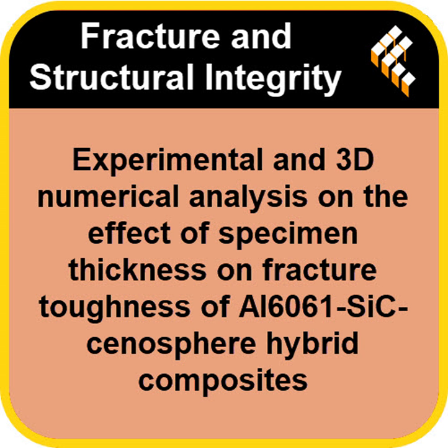Absolutely. Good practice. The researchers performed 3D finite element analysis, FEA, using ANSYS software. They used it to simulate the stress intensity factor, the SIF, at the crack tip. And the results from the simulation lined up remarkably well with the actual experimental data. They reported percentage errors generally below plus or minus 10%. Wow, that's pretty close agreement. It is. That convergence between the lab results and the computer modeling really affirms that their predictive model is robust. It means design engineers can likely use this model with some confidence.